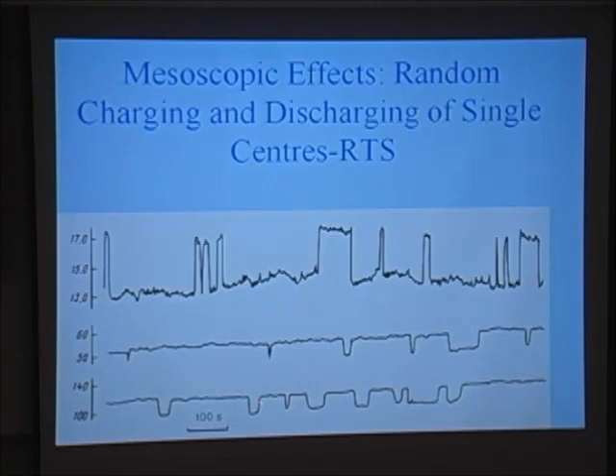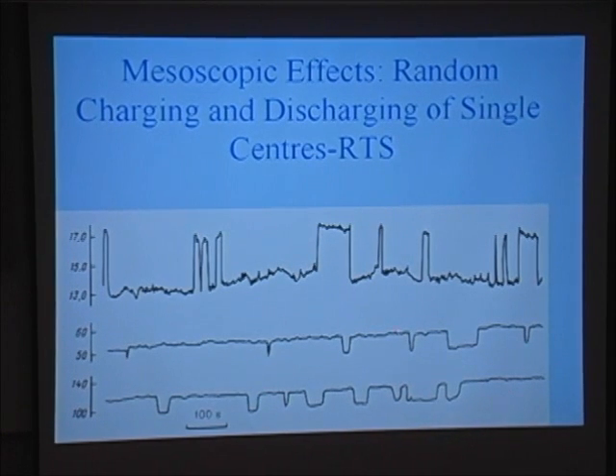Here we see the so-called RTS, random telegraph signals. This is what happens if you take a small piece of semiconductor and look at the resistance as a function of time. The units are fairly arbitrary, but this is what happens as a function of time. It fluctuates like that. And what that is caused by is that every semiconductor will have some defects, some impurities, some traps, which will just charge and discharge.